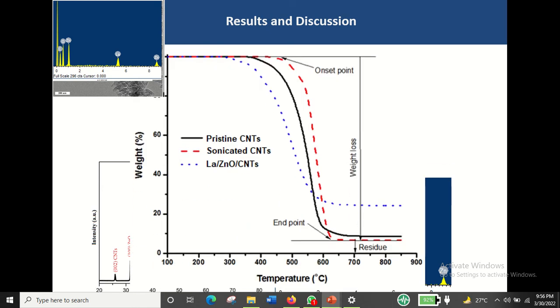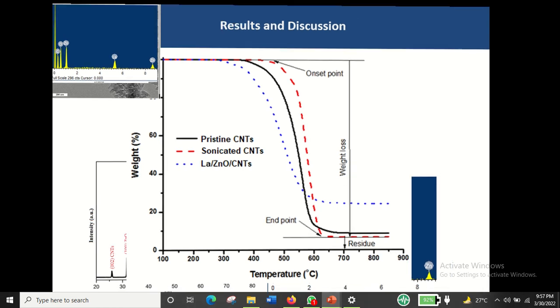Then we conducted the thermogravimetric analysis to check the stability of the structure and the residue present in the sample. We see that the pristine carbon nanotubes show low residue as compared to the composite photocatalyst. Since the composite photocatalyst consists of different materials which have different temperatures of degradation, the residue was much higher as compared to the pristine carbon nanotubes.